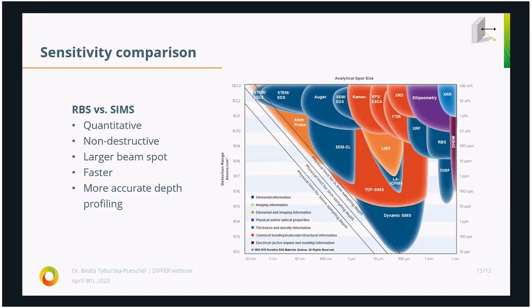Everything depends on the beam current. For polymers or very delicate samples, indeed, you would have to use very low beam currents. And of course, it's also the amount of fluence, so shorter measurements. At the end, RBS can be a little bit destructive, but if you have shorter measurements, so less fluence and very low beam current, then there should be no problem.